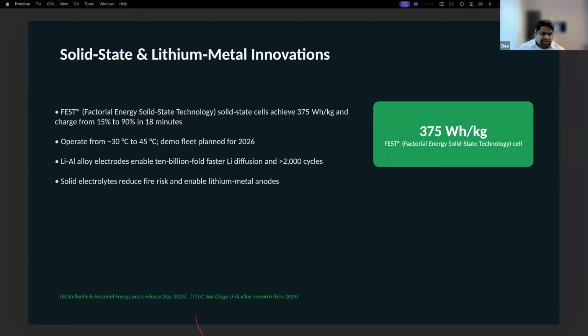existing lithium-ion chemistries. So what it does basically is it replaces the flammable liquid electrolyte that's been used in most of the batteries that we have at the moment, including the one in our phones, and the separator. So it replaces the liquid electrolyte and the separator with a solid electrolyte, which enables the use of lithium metal anode. This promises much higher energy density, improved safety, and faster charging. So who is pioneering this?